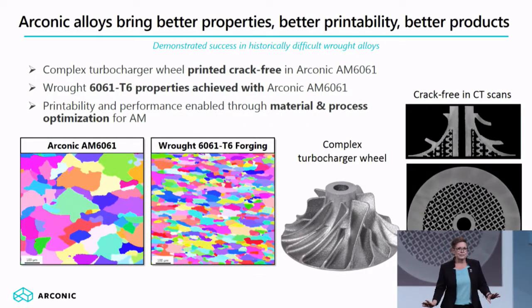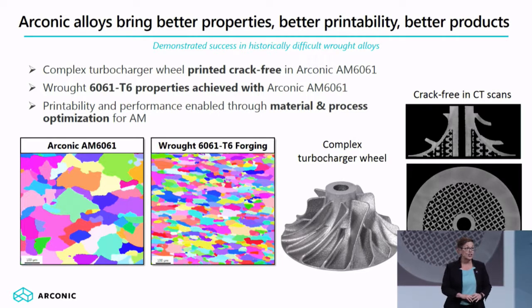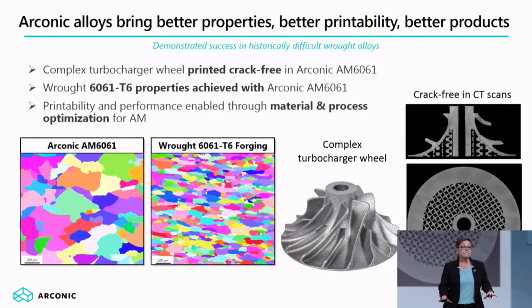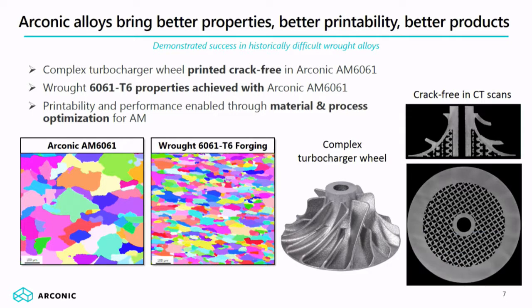So, in addition to these two alloys for elevated temperature applications, Arconic is also developing AM versions of traditional wrought alloys. As Sean previously mentioned, the 2000, 6000, and 7000 series aluminum alloys are historically prone to solidification cracking issues. What you see here is that Arconic has developed its own AM version of 6061. We've shown with that alloy that we can build complex 3D parts and show that they are crack-free. In addition, we meet the tensile properties of conventional wrought 6061 T6.